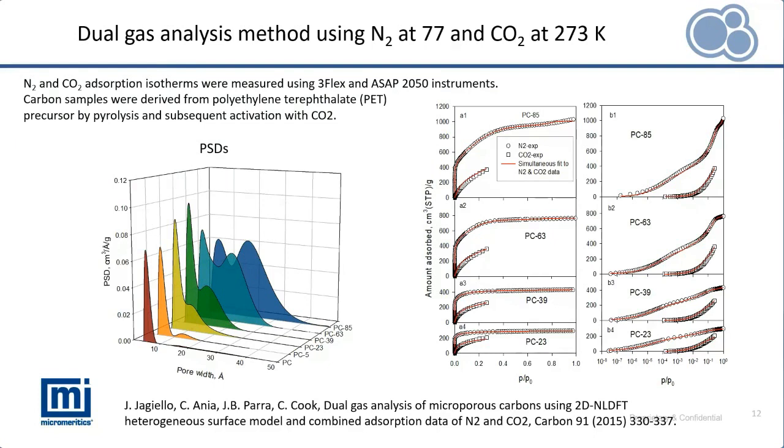Here we measured nitrogen and CO2 isotherms on a series of samples derived from PET by pyrolysis followed by activation with CO2. We obtained an excellent fit to CO2 and nitrogen isotherms for all samples. This demonstrates the consistency between the two kernels.